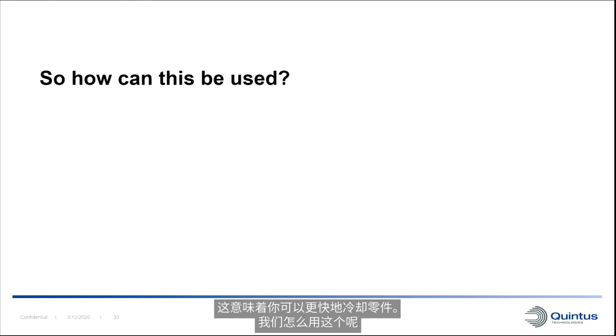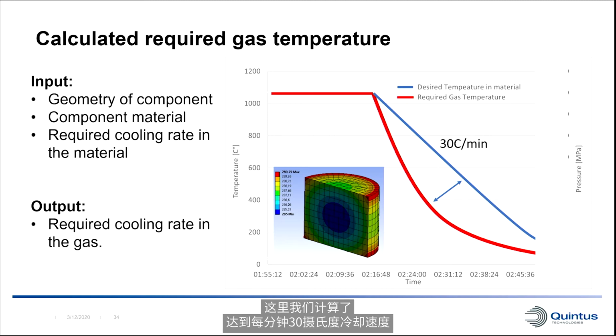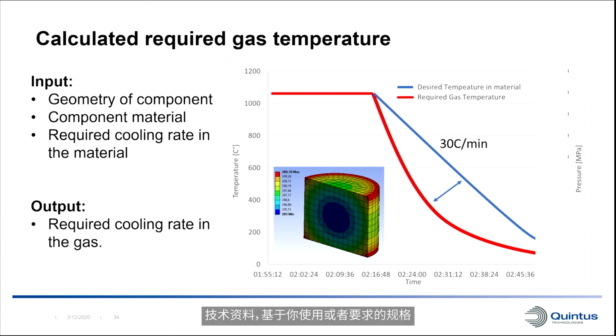So how can we use this? Here we've calculated the required gas temperature to achieve a 30 degrees C per minute cooling rate. The geometry of the component is needed, of course, for this. The material with the required data there, the technical data, but also the required cooling rate in the material based on the specifications you're using or your own demands. And then the output is the actual gas cooling rate that we need to ensure that the machine can do for you.